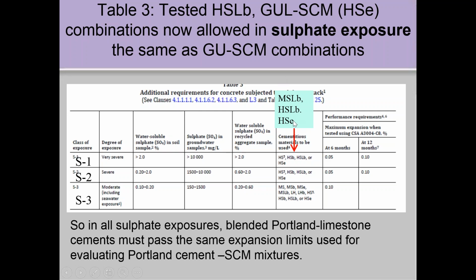And we've also added HSE, an equivalent, because some specifiers, especially in Alberta, were not allowing ready-mix companies to supply a GU cement plus, say, a slag or a fly ash as equivalent to a blended cement. They said, well, it's not on the list. So we've created HSE as equivalent to a high sulfate resistant blended cement to say that if you make SEMs, you can use GU cement and call it a sulfate resistant equivalent. And it seems like common sense, but there were some designers, certainly in Alberta, that were not accepting this, which was causing problems. And so you can use those cements, and then for anything that's not a straight Portland cement, there's performance requirements in terms of a mortar bar expansion test. That's always been there.